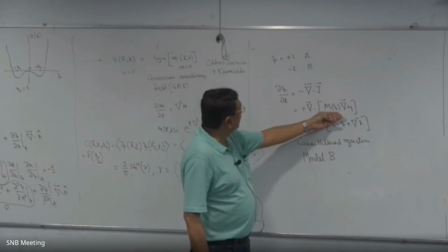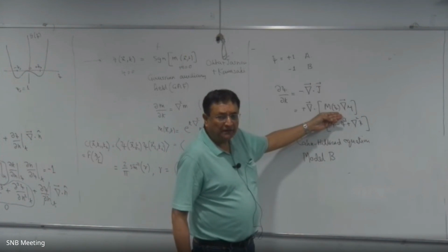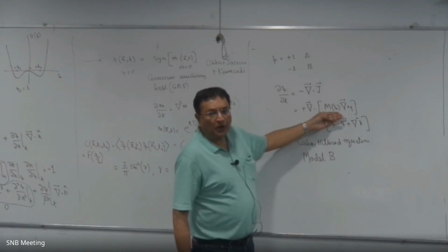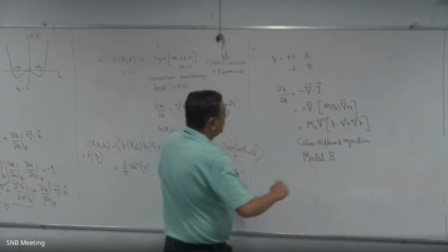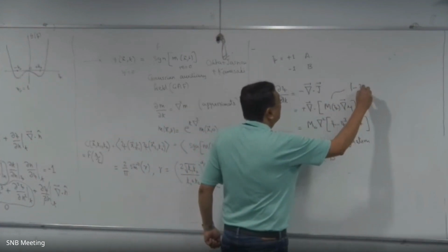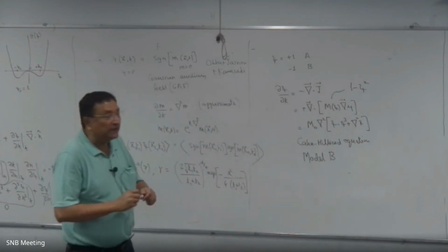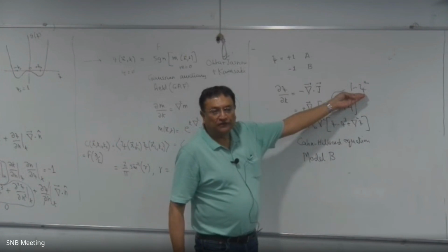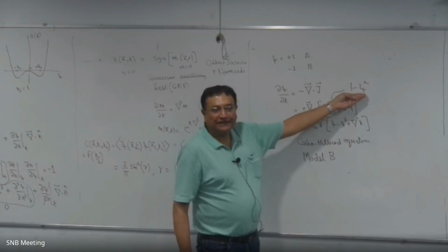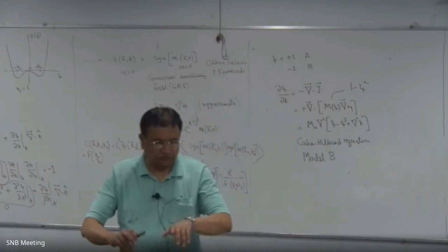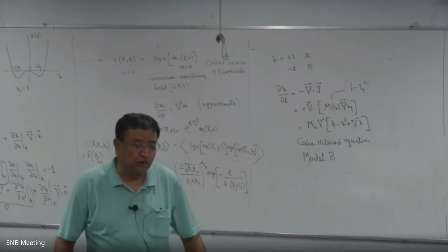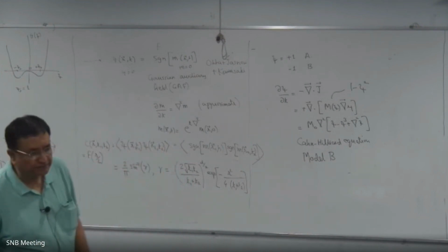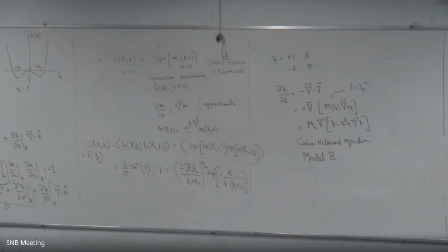Maybe for the diffusion equation, you can have forms of M. So in this case, the two popular forms are one, it's a constant, and two, where it goes as 1 minus psi squared. That's called order parameter dependent mobility. What this does is it cuts out the current in the bulk of the domains. So there's now only current at the interfaces, and that's surface diffusion. So material transport is along the interfaces. And that opens up a whole new kettle of fish. Different growth laws. Numerically also it is not known. If I want to calculate exactly, say in one dimension, simplest case, it is not known.